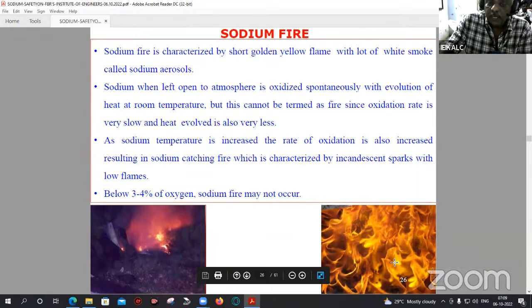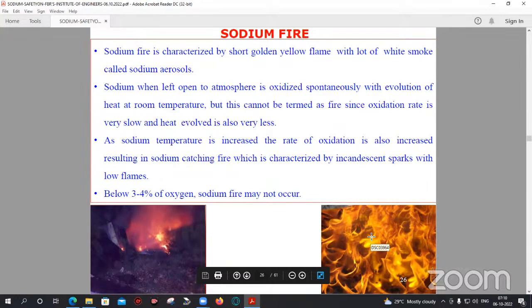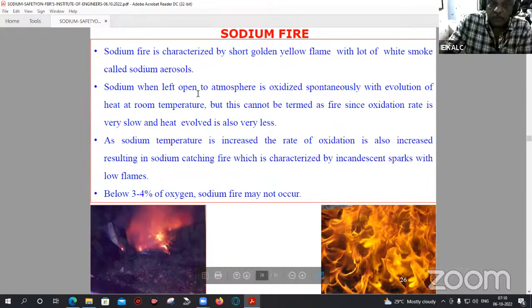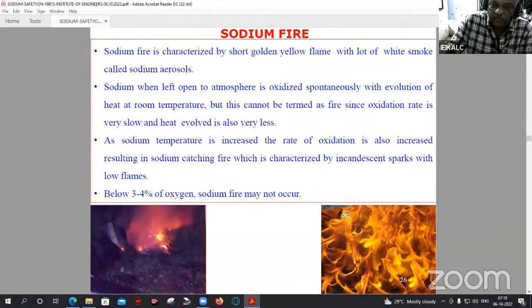But the issue is white dense smoke, aerosols. And this sodium, when left open to atmosphere, is oxidized spontaneously with evolution of heat at room temperature. But this cannot be termed as fire since oxidation is very slow. As sodium temperature is increased, the rate of oxidation also increases, resulting in sodium catching fire. As I already said, at almost 270 to 300 degrees centigrade, if it leaks, sodium will catch fire immediately.